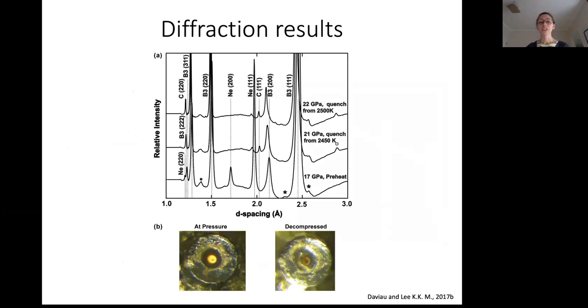So again, jumping into diffraction results of our pure silicon carbide heating. We heated that B3 zinc blende silicon carbide with neon as our pressure medium. Down here on the bottom, this first pattern is a preheat pattern where we just have the silicon carbide and our neon and some gasket diffraction. As we increase temperature, we're looking to see either the appearance of carbon, silicon, or maybe some kind of indication of melting. And what we do find is that carbon diamond diffraction begins to appear in the patterns.